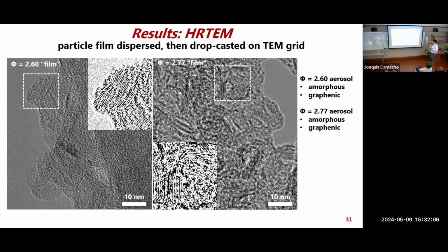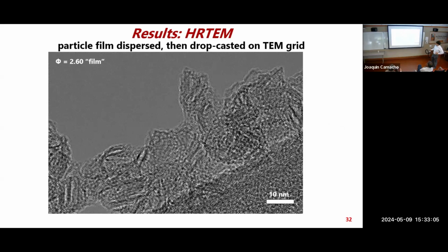And then taking another measurement technique, taking the film that we collected over time, scraping it into a powder, and then drop casting it onto a TEM grid, we see a similar result, but it might be even a little more crystalline. And there is definitely similar evidence of this graphene-like structure. So this here looks like a little bean, with this more uniform structure, and you can see these ribbons. So this is not soot. It's hard to avoid these things coagulating because it is a powder that deposits, and then when you try to collect it, disperse it into a droplet, and coat a TEM grid with this, it dries up, and as it dries, it coagulates. It bunches up again. So it's very hard to disperse these. But nonetheless, you do see clear, straight lattices, unlike soot. Here are more examples. This is not soot; it's just graphene type materials.